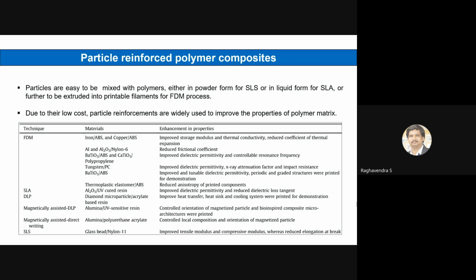There is one more example of aluminum and aluminum oxide. It is fused with nylon 6, and this is used to reduce the frictional coefficient. The third example is barium titanate with ABS and calcium titanate with polypropylene, PP. That can be used to improve the dielectric permittivity and controllable resonance frequency. And one more example is tungsten with polycarbonate. All these examples tell you that you can go beyond thermoplastic. You can go one step next to FDM by converting this into an advantageous technology.